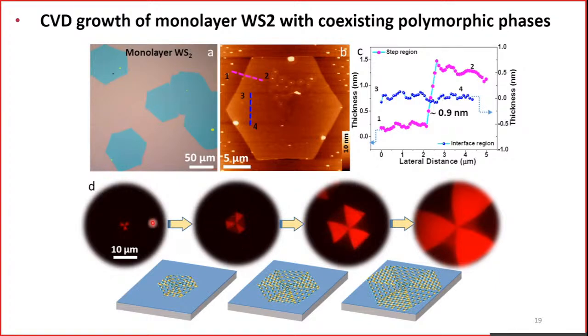So this we are observing from very, very small size, even less than a micron, right? And we have seen in the confocal microscope to some extent. But clearly, after a few microns where we are able to resolve, there are two different contrasts emerging and growing as a function of time. But when we try to do a line profile analysis using AFM, is there any difference in the thickness? Because immediately when we see optical contrast, we thought maybe this is a monolayer, this is a bilayer, probably not emitting because of indirect band gap. But absolutely we don't see any thickness contrast, any thickness variation across the interfaces.